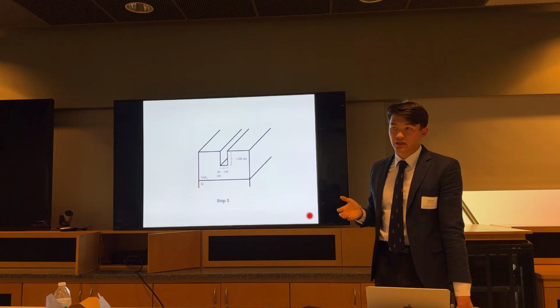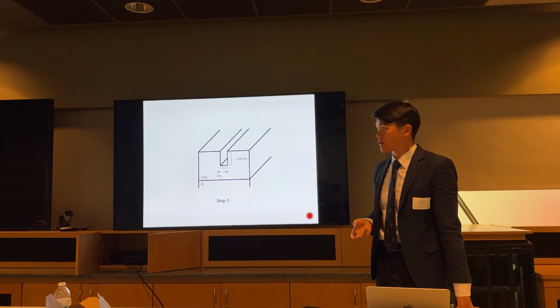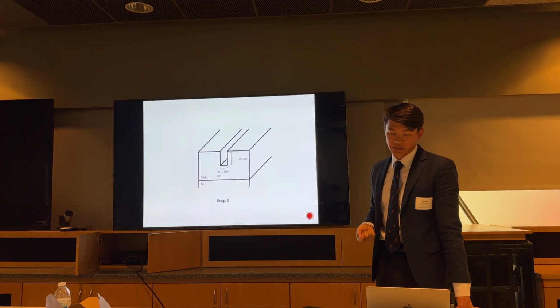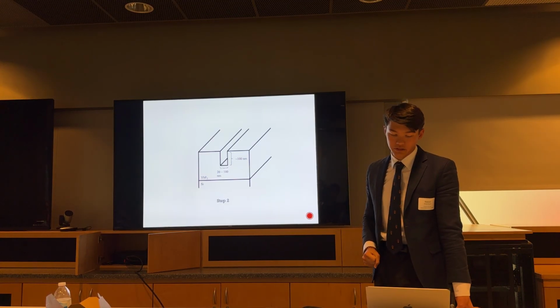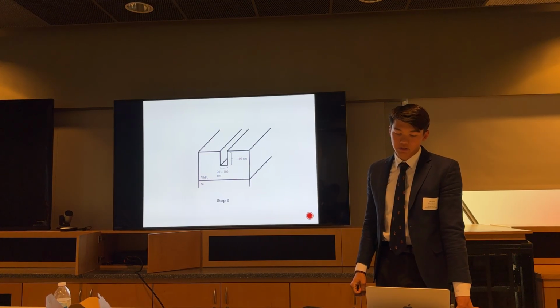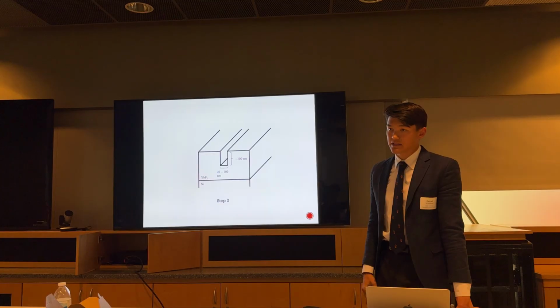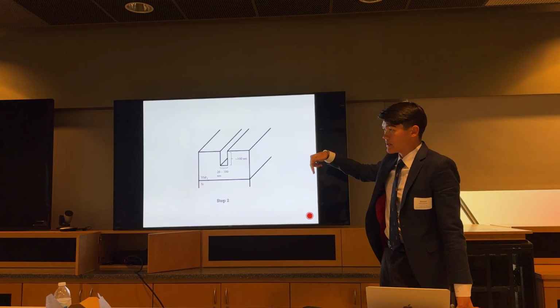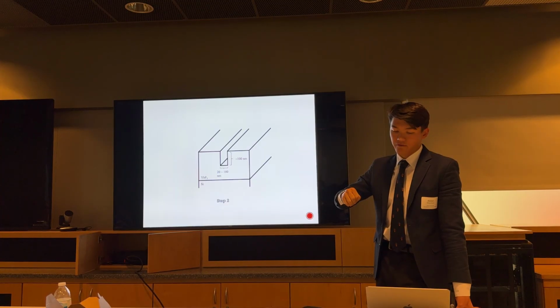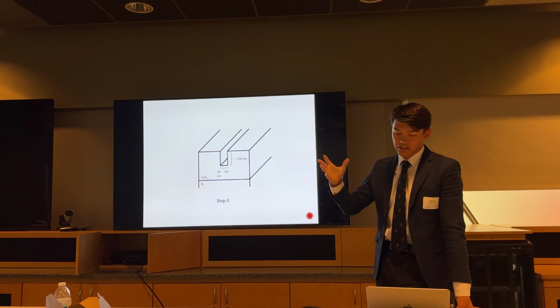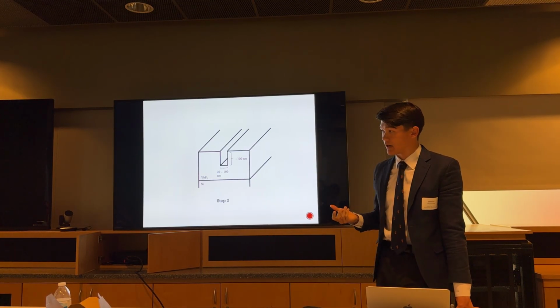Now, there are two main reasons we chose ytterbium fluoride. One is it's an ionic material, so it has very high resistivity, and so it won't mess up the electrical characteristics. But also, very interestingly, it's a self-developing electron beam resist, meaning if you hit it with an electron beam, the material itself will essentially evaporate or disappear, leaving behind a trench.